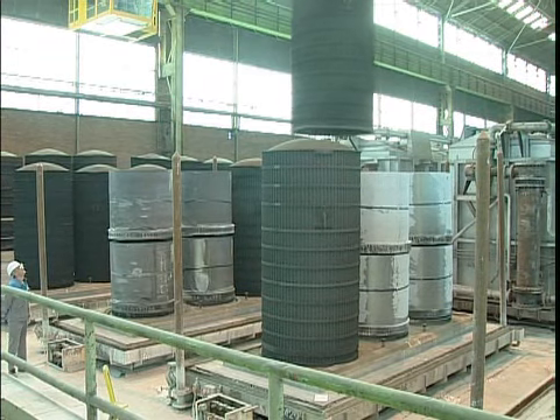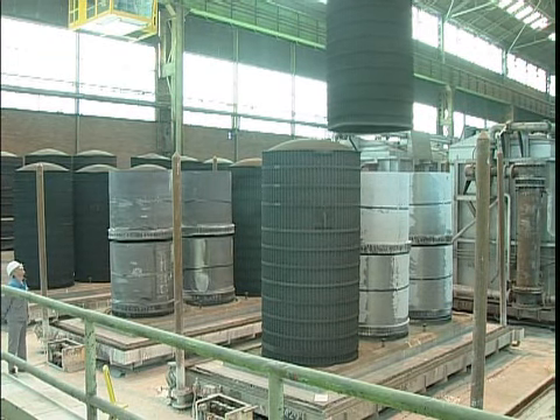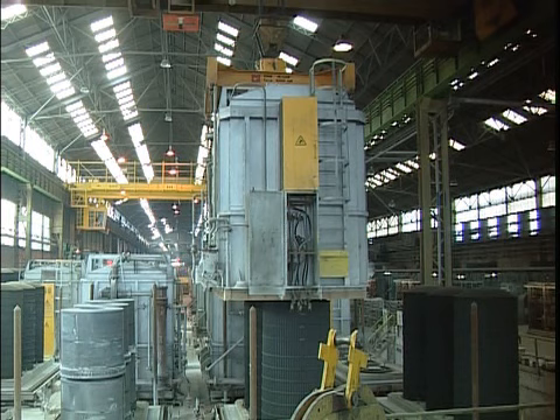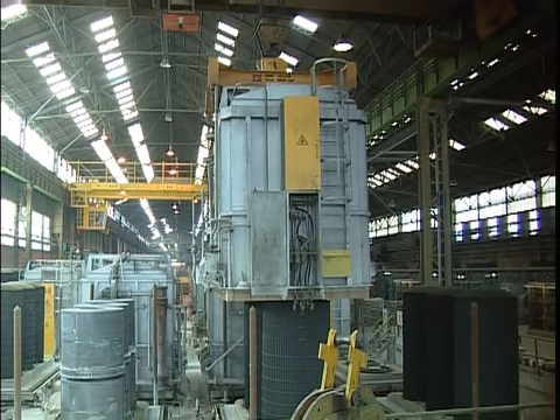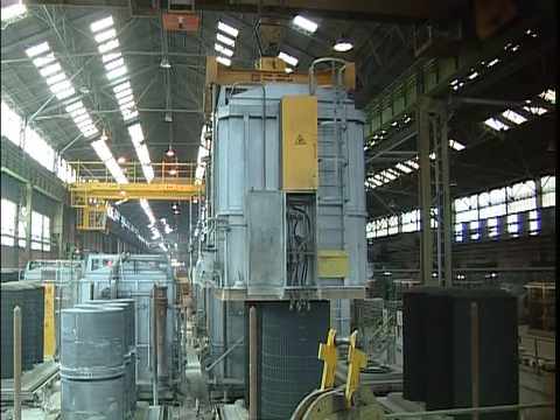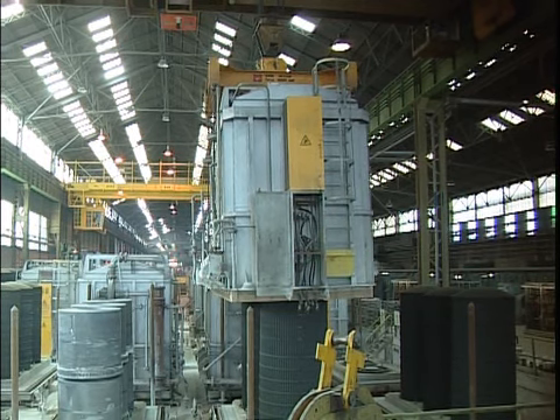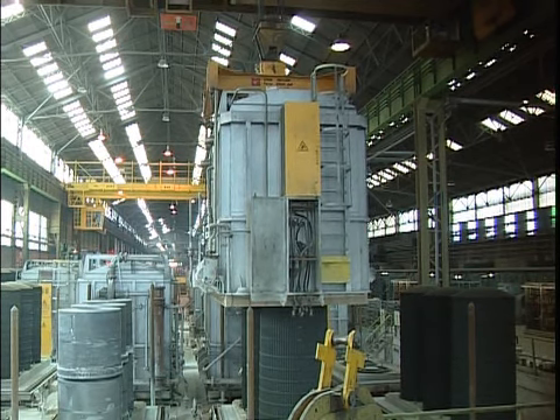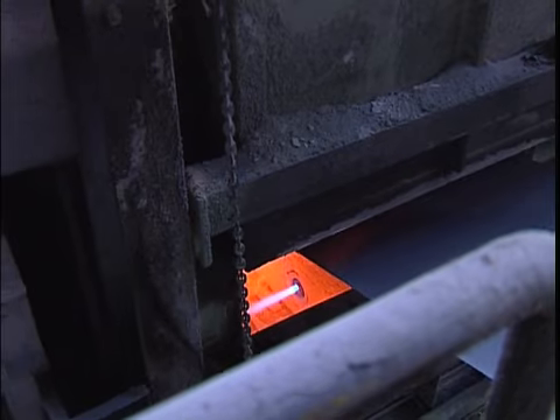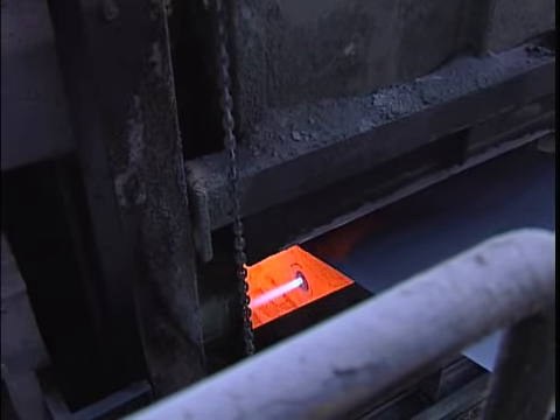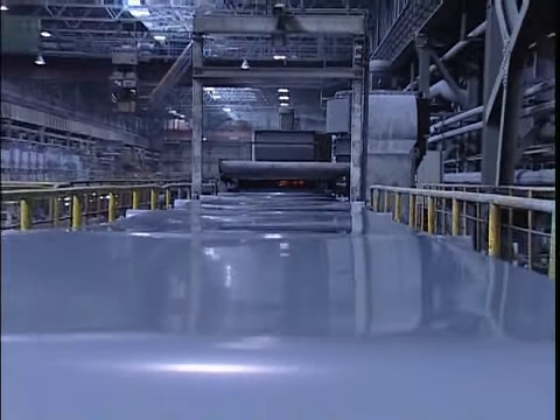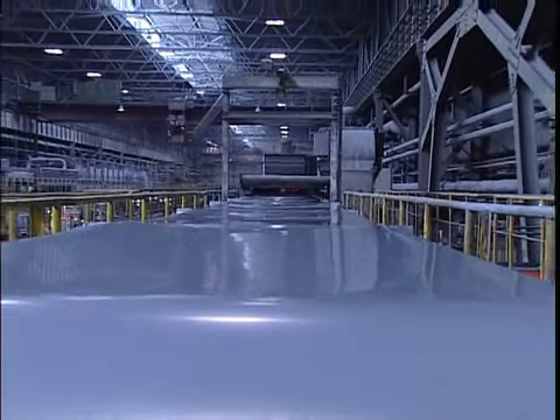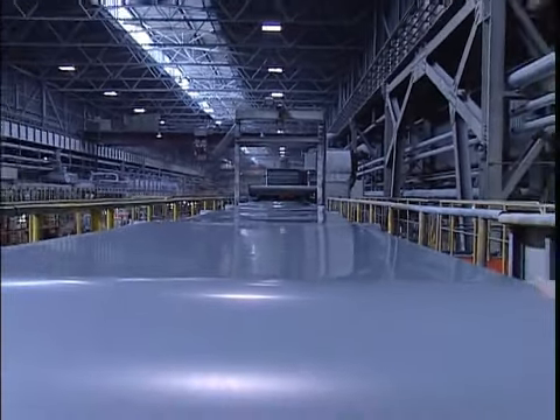A protection hood constrains the required reaction gas for a stack of 2 coils at a time. A heating cover over a total of 3 stacks, fitted with electric elements, provides the heating and also controls the cooling process, lasting several days. The following continuous annealing and coating line provides an insulation coating, a thermal flattening, and a stress relief anneal.